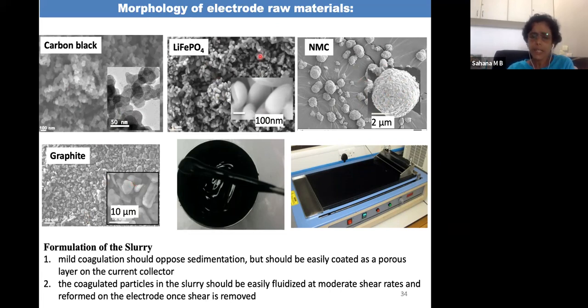So when we prepare a slurry out of any one of them, and carbon black goes with all three active materials, we should optimize the preparation of the slurry. After preparing the slurry in a plant, we prepare a slurry of say 5 liters, 10 liters, or in an actual plant thousands of liters. We cannot coat that in one stretch, right? It takes a little time to coat. So during that, the particles should not sediment. If sedimentation takes place, then we will not have a good electrode coating.